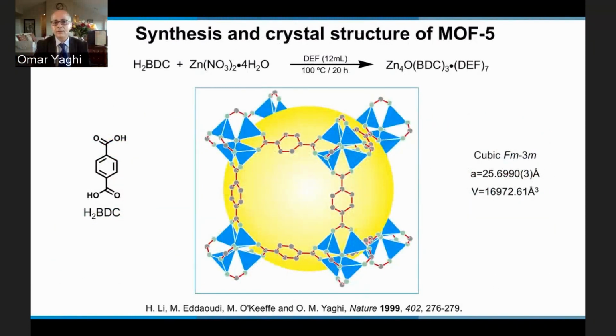So the way to make a MOF hasn't changed much from what we reported in the mid-1990s and in this report in 99 for MOF-5, which is to take an organic acid and deprotonate it by, in this case, DEF, which has base present in it when heated. That base deprotonates the acid, and then the carboxylate reacts with the zinc to make an extended structure.